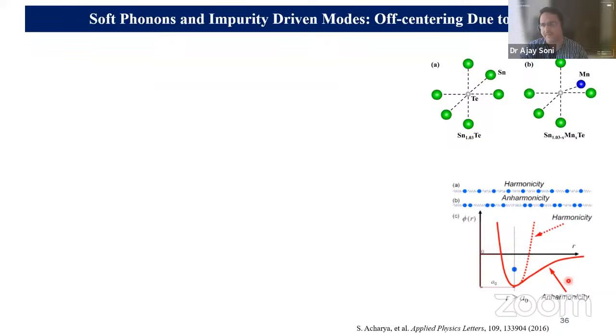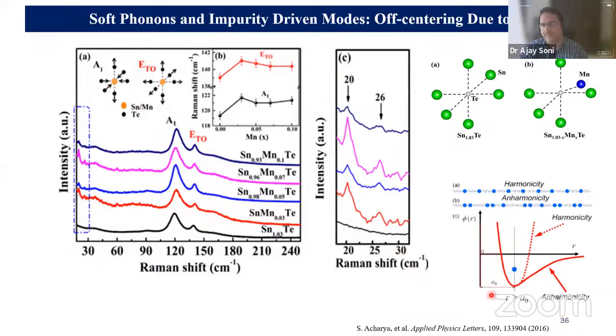actually creates new modes which have been seen in the Raman spectroscopy of these materials. So you can see this Mn doping. This is pure, and there is a slight jump in the two modes. These two modes represent the phonon modes, or the atomic vibrations, or they represent the chemical environment around the tellurium. So if the chemical environment around the tellurium changes, you have a shift in these modes, which is visible here.